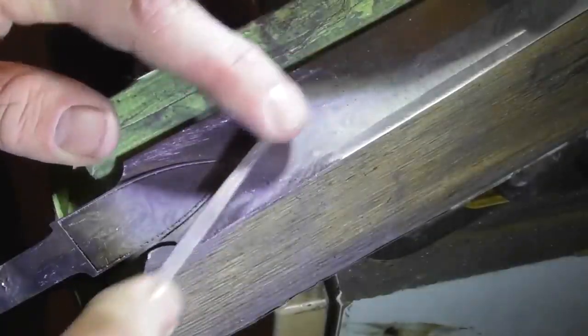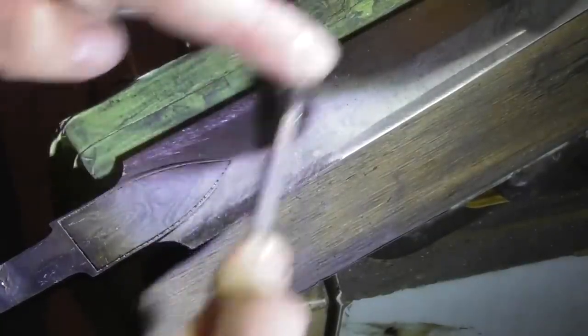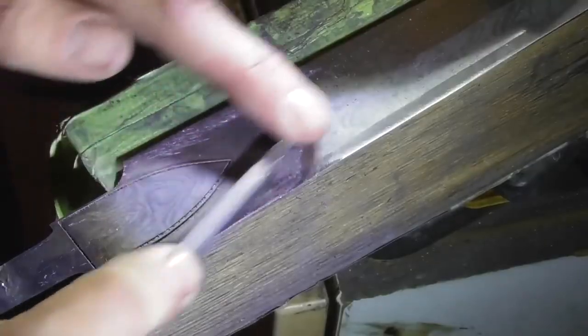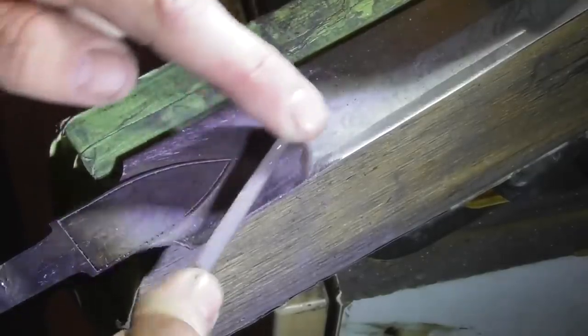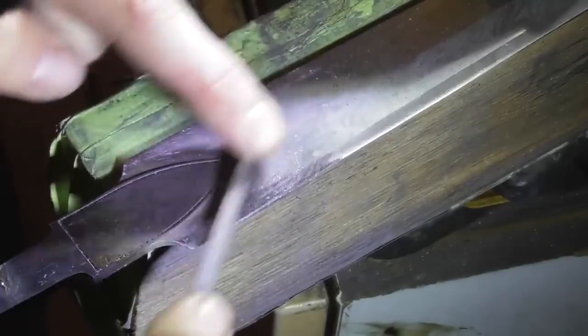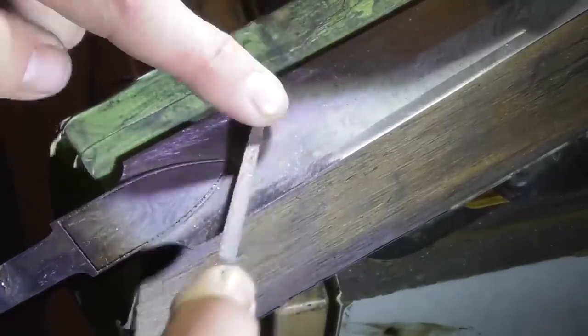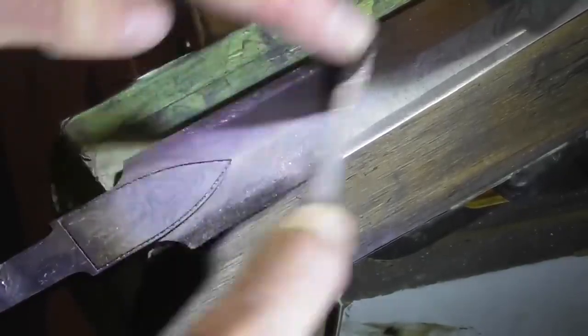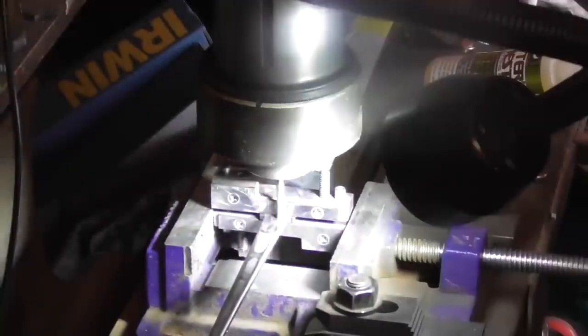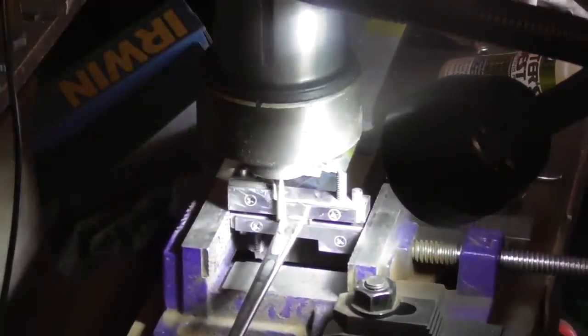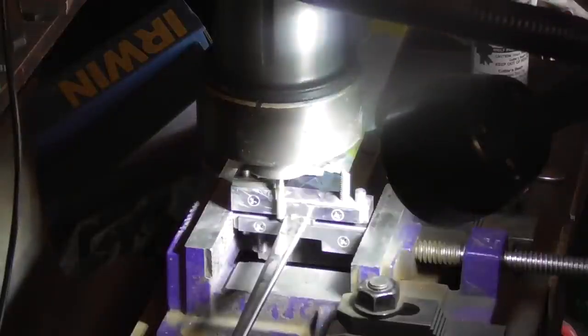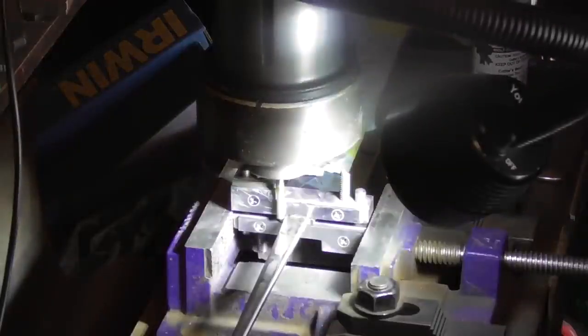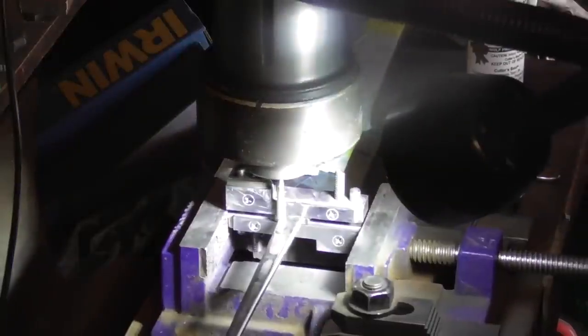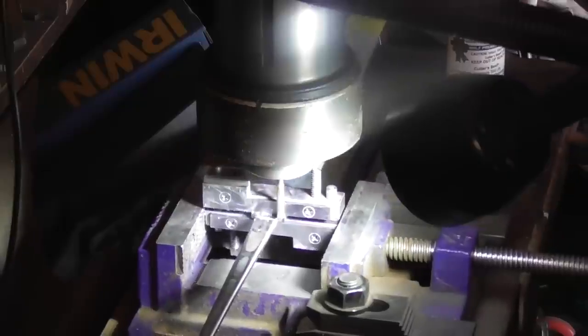So because of how the ricasso is, when I was putting the edge on there, I wasn't able to put it on the area near the ricasso. So now I'm going in with diamond files and putting that edge on the ricasso area, and then I hand sanded that out and cleaned it up too. Once that's done, I go over to my milling machine and I am just putting a tiny little shoulder where the tang meets the ricasso area, anywhere from like 5 to 10 thousandths down.